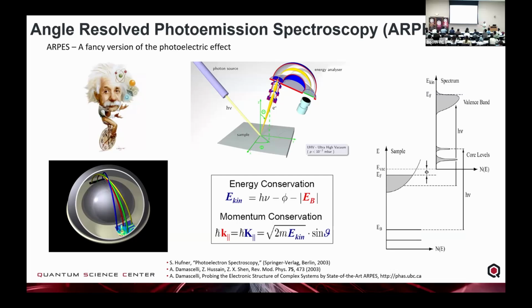And so what we do in ARPES is we shine the light on there, and as these electrons come out, we have these hemispherical analyzers or time of flight analyzers, where we measure the energy and the momentum of these electrons as they come out of the material. Using some very simple conservation rules, we can understand how that electron was behaving inside the material. With the hemispherical analyzer, we look at the angle, which defines the momentum of the electron, and then the trajectory around this hemisphere, which defines the energy of the electron. So here we can see one axis of momentum, one axis of energy, and then we can take our sample and rotate it to access the other parallel momentum space.